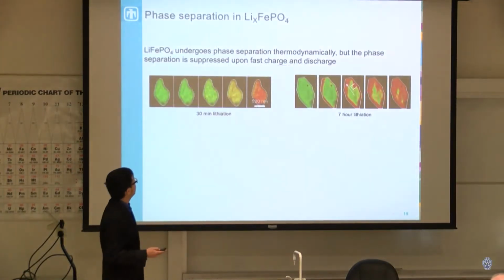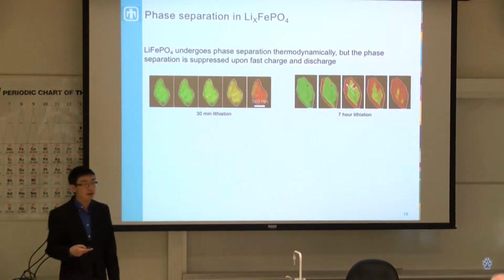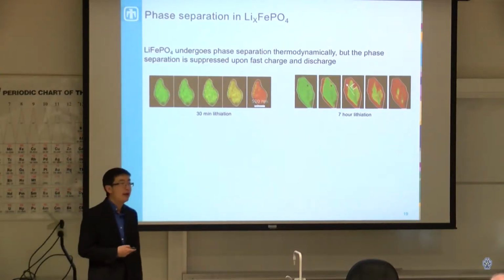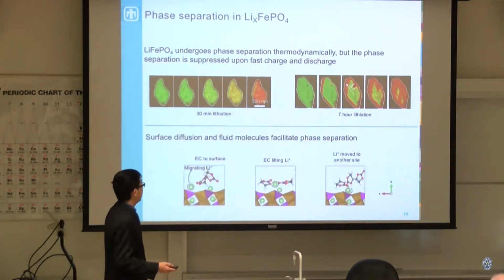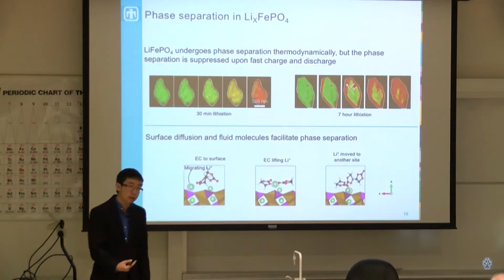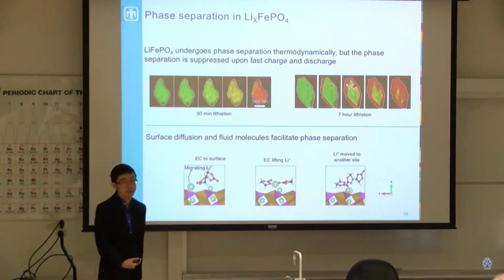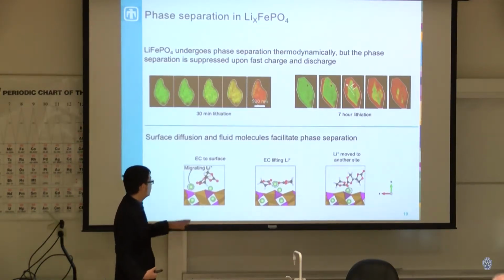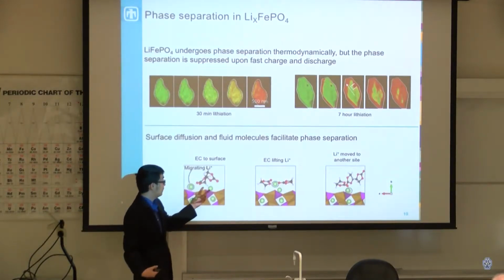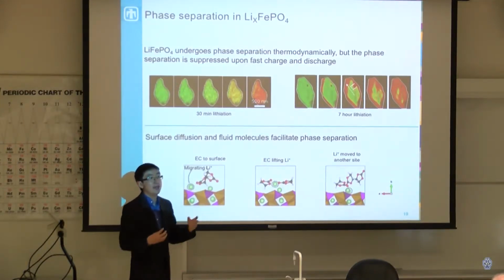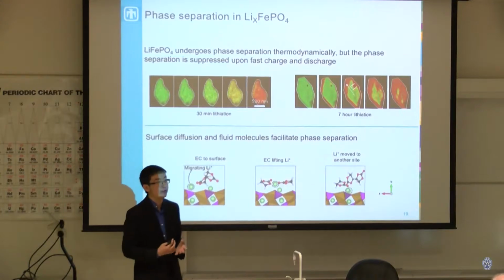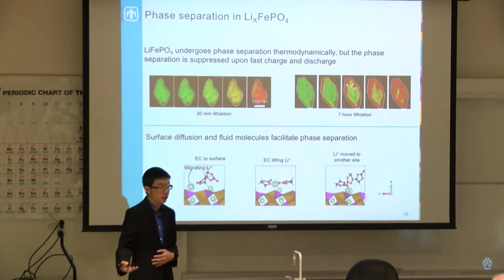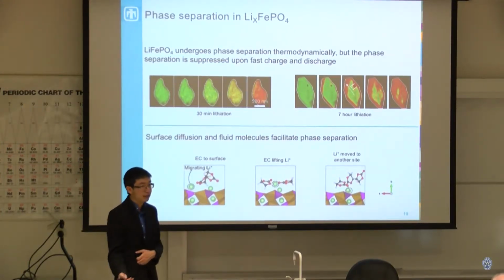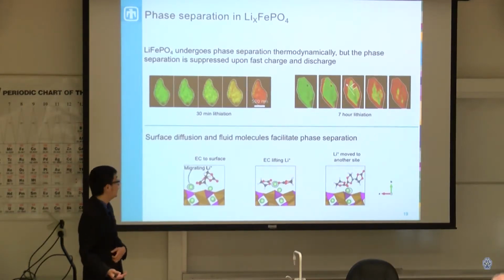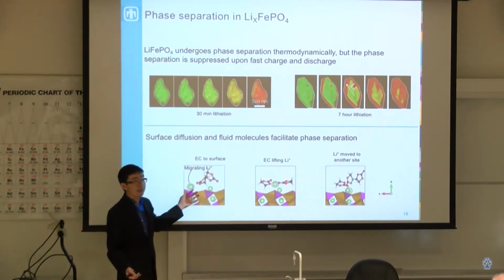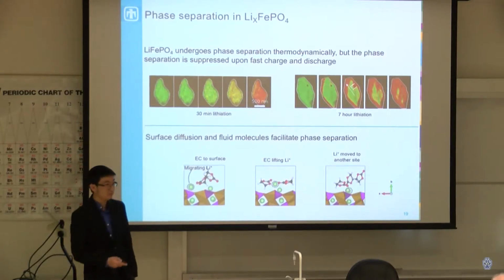To summarize the results, lithium iron phosphate undergoes phase separation at lower cycling rates and solid solution at higher rates. But the origin of this phase separation, and one way that we can potentially suppress it, is the fact that lithium can get picked up by these electrolyte molecules and be shuttled around the surface very quickly, such that it is going towards this lowest energy phase separation pathway. So if we want to suppress phase separation, we have to suppress the migration of lithium along these surfaces.